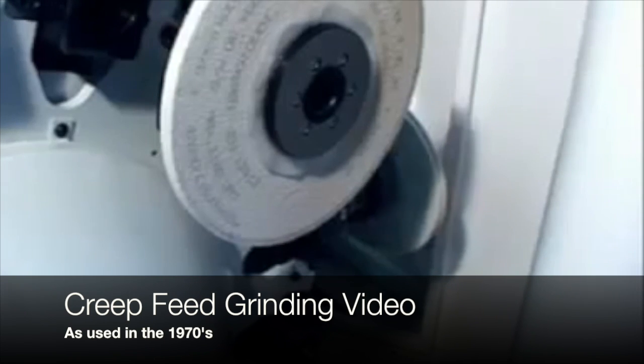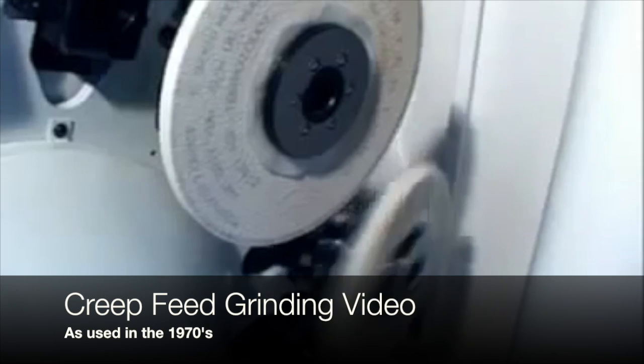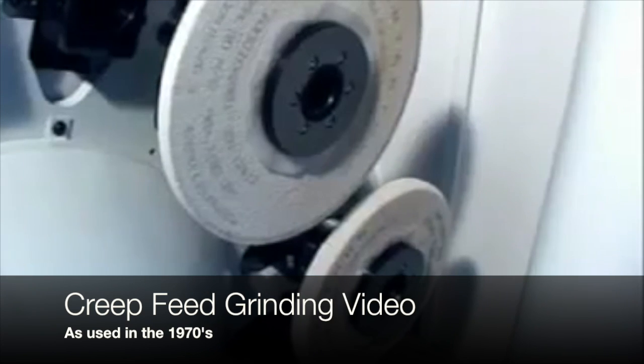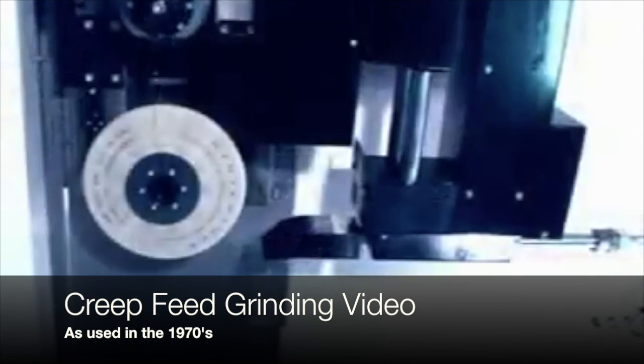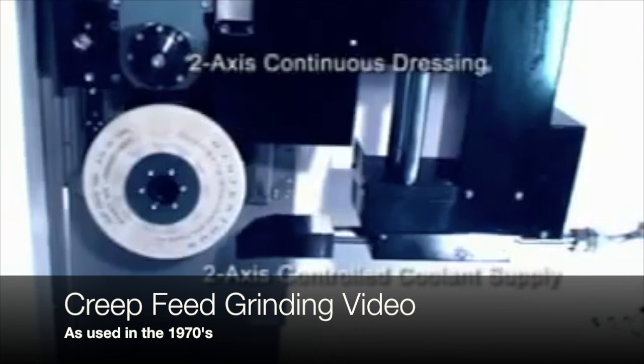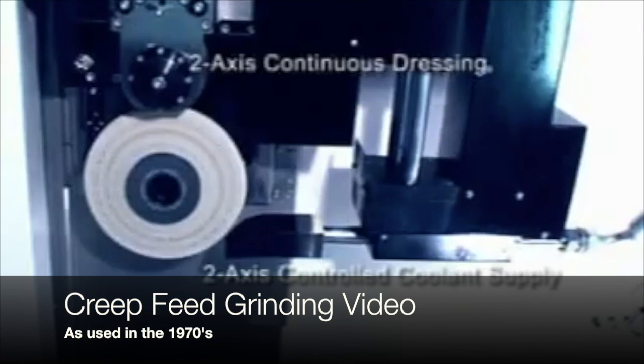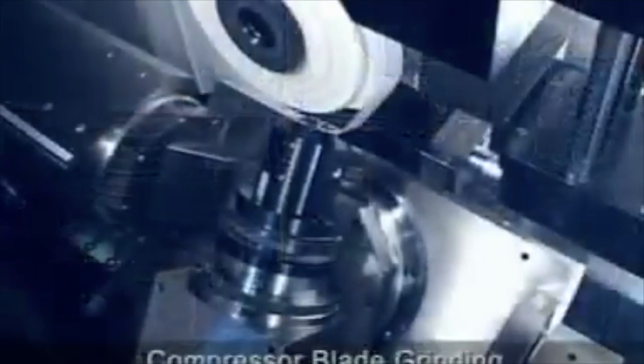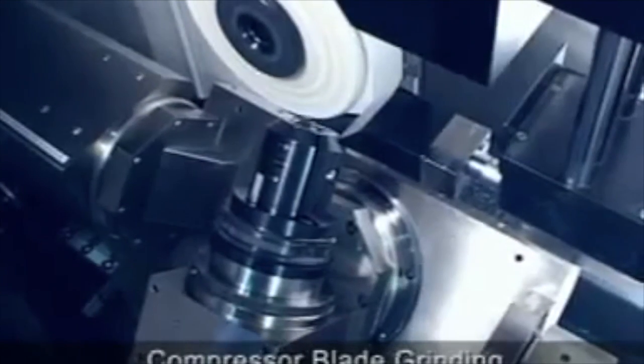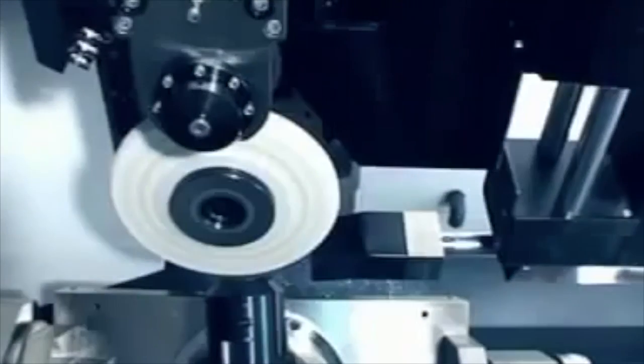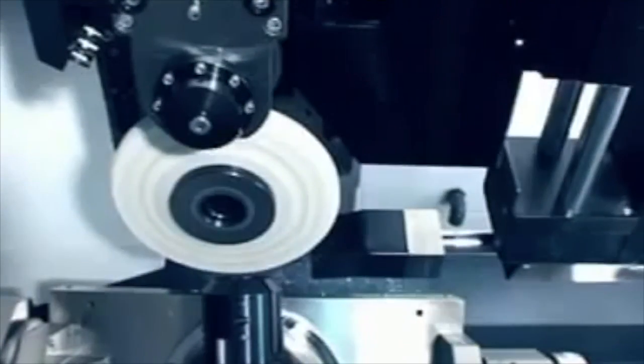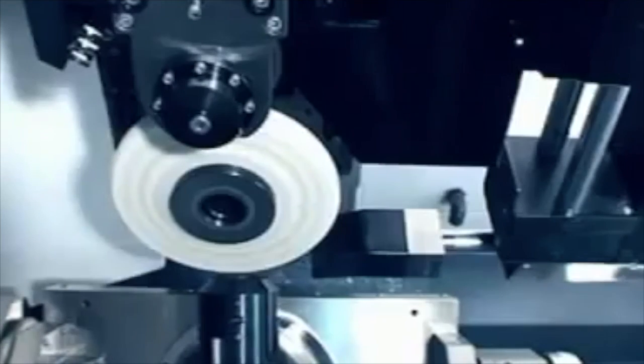In creep feed grinding, the machine table feeds a workpiece in the direction of the grinding wheel rotation. While the table speed is low, the depth of cut is very high, which results in a high removal rate. There are two key attributes that emerged that would have a significant impact on the productivity of creep feed grinding, which are the cooling supply and the wheel dressing. The supply of coolant to the grinding wheel is vital in the grinding process.